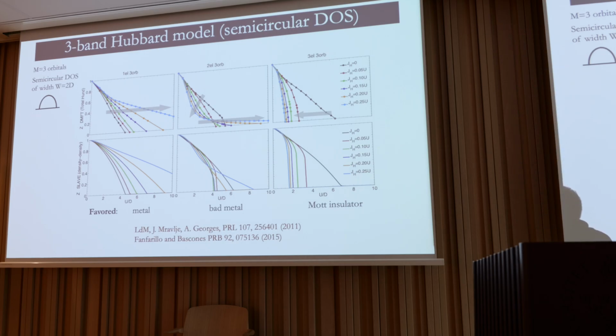You can forget 1 electron in 3 orbitals or 1 electron in 5 orbitals. When you have just 1 electron or 1 hole, there is no Hund's coupling really doing a lot. But in the cases which are not half-filled and not extremely empty or filled, you have two effects fighting each other. The charge fluctuations are favored, but the splitting of the degeneracy of the ground state makes the quasi-particle heavy. So we call this the Janus phase, because of some Roman god that has 2 faces looking opposite ways, since these two effects really fight against each other.